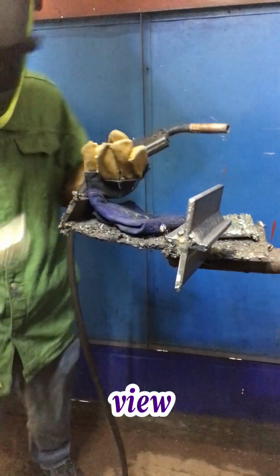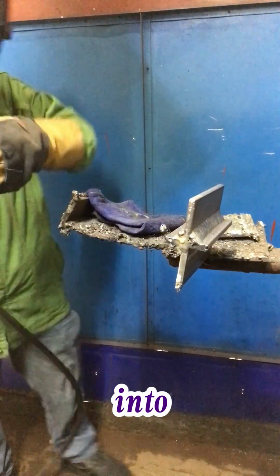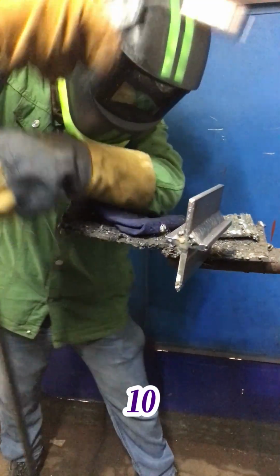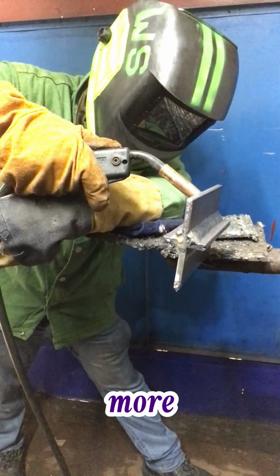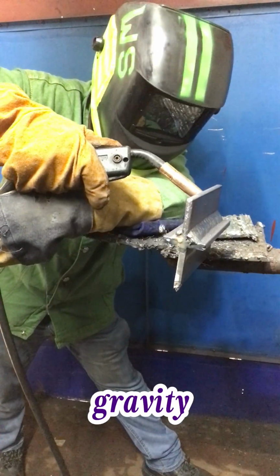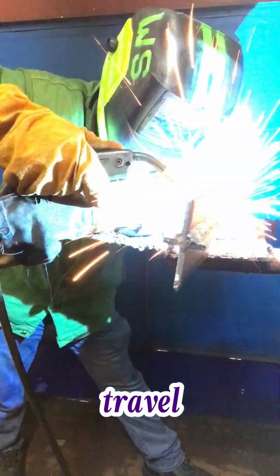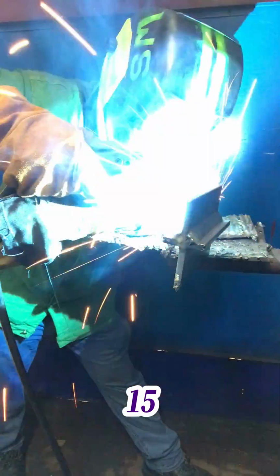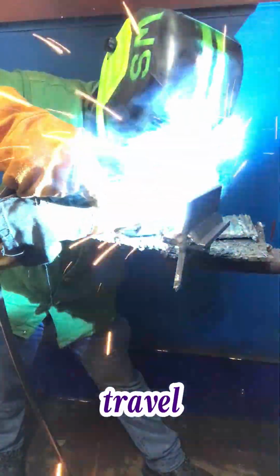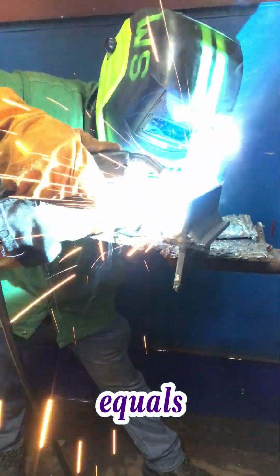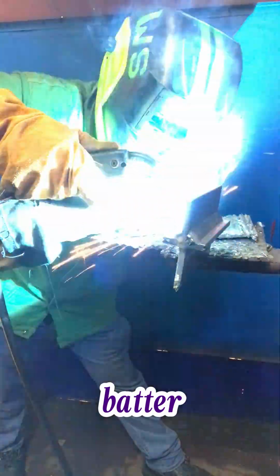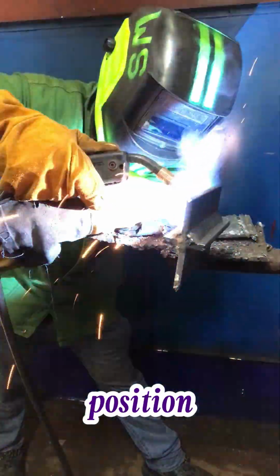Work angle: side view, 45 degrees pointing directly into the corner. Tilt 5 to 10 degrees toward the top plate. This puts more heat on the upper leg to balance gravity and prevent sag. Travel angle along the weld, 5 to 15 degrees pull, gun points opposite the direction of travel. Pull technique equals better control, less spatter, and a cleaner bead in the horizontal position.